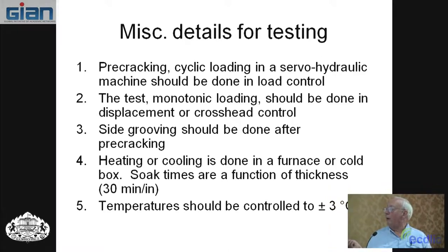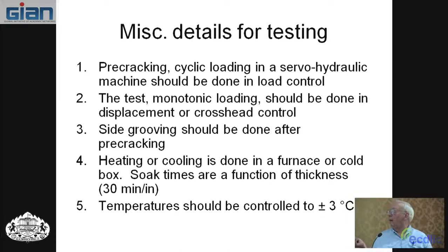If you're pre-cracking, you need to have load control pretty much for your pre-cracking. However, when you do the test, load control isn't good. You should use displacement control or crosshead control, depending on the machine.